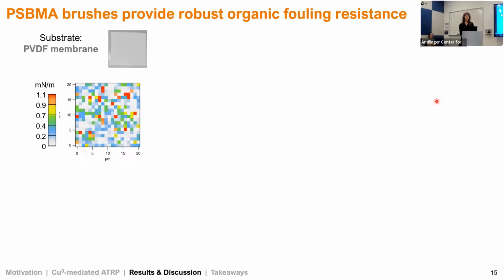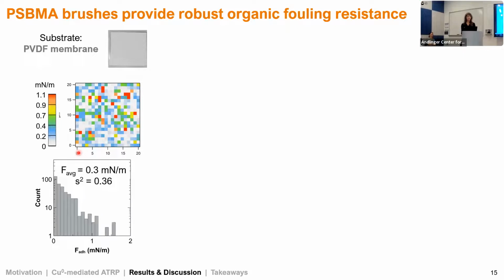Okay, so starting with our model organic foulant, here we have our unmodified membrane, and these are just the same results from the previous slide. All I want you to really focus on here is the color. The higher the adhesion force is, the worse. So basically we don't want to see any red. We want to decrease the adhesion force to improve fouling resistance. We can also look at this quantitatively with a histogram of our adhesion forces. Here we have the average adhesion force and also the variance, both of which are relatively high for this unmodified membrane.